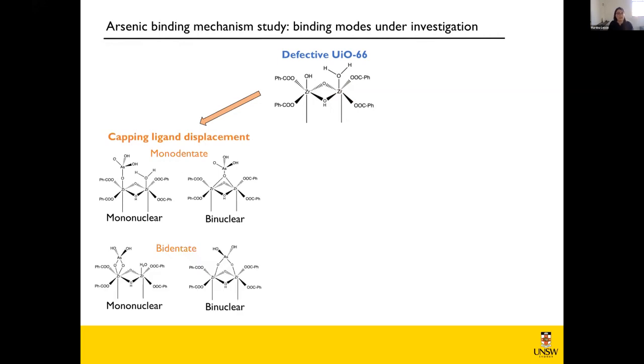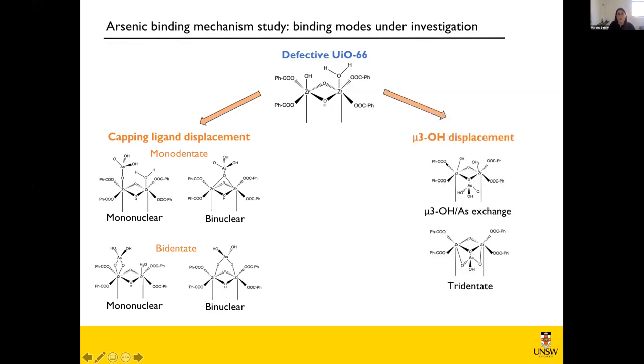The other option is to have bidentate binding modes, where two oxygens join in and bind to either one zirconium or to both zirconium atoms. The other option proposed in the literature is that instead of the ligand being displaced, we might actually have these mu3-OH species being displaced, and then arsenic comes in and saturates the zirconium in its place.